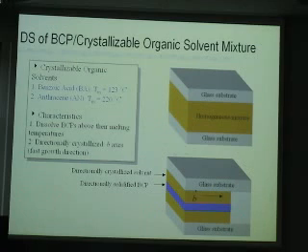So it's a homogeneous liquid. And since we are interested in thin film application, we confine the geometry by using this substrate. So initially we have a homogeneous mixture at high temperature. And then when we decrease the temperature, the benzoic acid starts to crystallize. But when benzoic acid crystallizes, it has a fast growth direction, which is the B-axis. The benzoic acid tends to crystallize very fast along the B direction of its crystals.